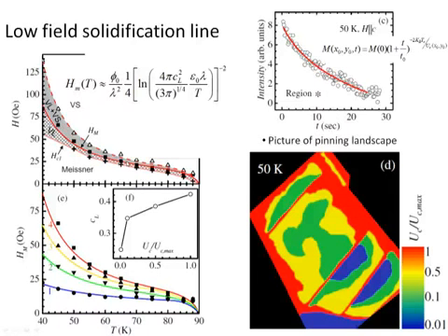in pin-free superconductors. Around this melting phase boundary, we have also identified a regime of coexistence where the vortex solid and liquid phases coexist. Using our magneto-optical imaging technique, we spatially resolve the information on relaxation of remnant magnetization at different locations in the sample, which we use to deduce the pinning landscape across the sample.